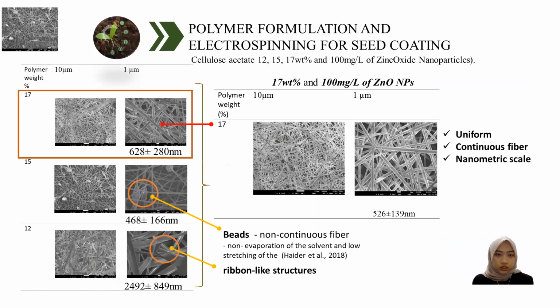As for the results of this study, we are utilizing different polymer weights of cellulose acetate and studying which concentration is able to produce a good fiber. Eventually, 12% and 15% nanofibers produced beads and ribbon-like structures caused by the non-evaporation of the solvent. This is not favorable, as it has high surface area and also microstructure. But eventually with 17% nanofiber, we are able to produce a uniform, continuous fiber within nanometric scale size, which is 526 nanometers.